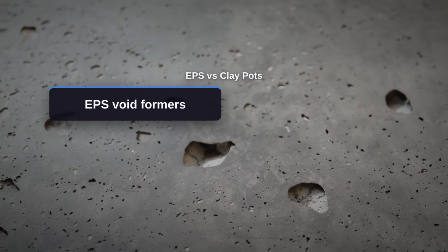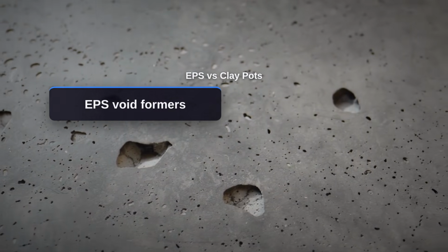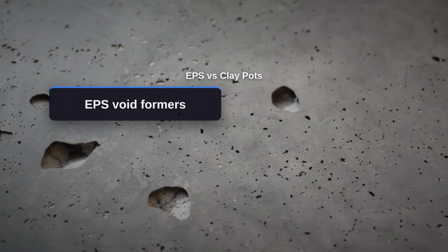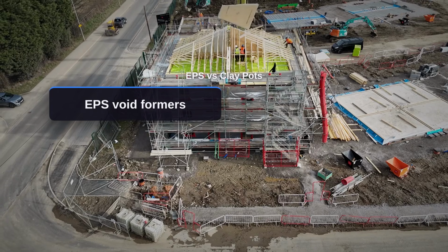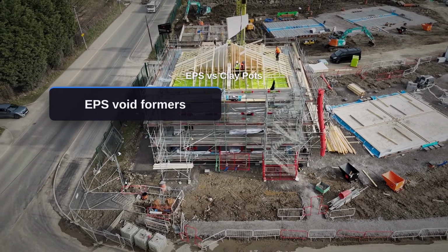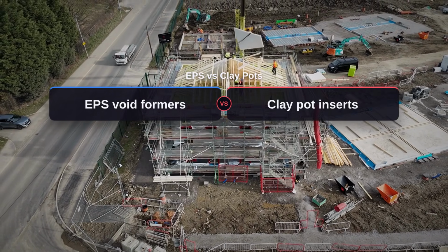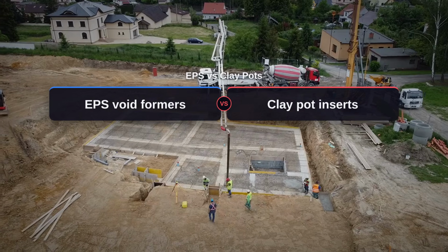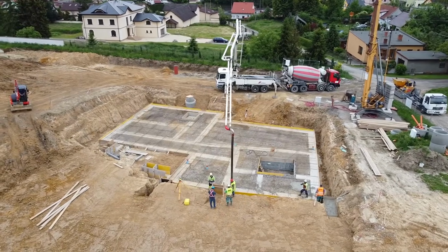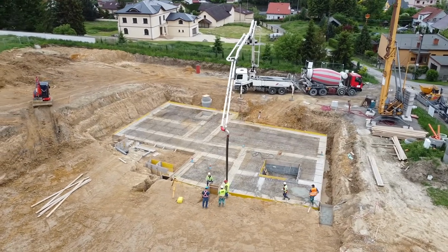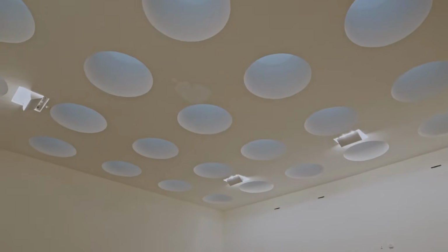EPS has very low thermal conductivity, around 0.04 watts per meter Kelvin, compared to clay's 0.8, so it performs better as a pure insulator. But it eliminates the evaporative cooling contribution of clay, and its embodied carbon is significantly higher. It also floats aggressively during a concrete pour, requiring mechanical restraint that clay pots don't need.